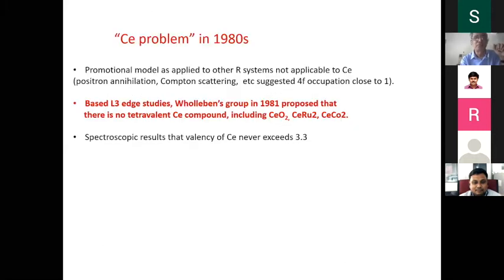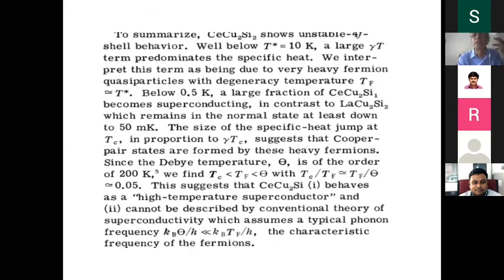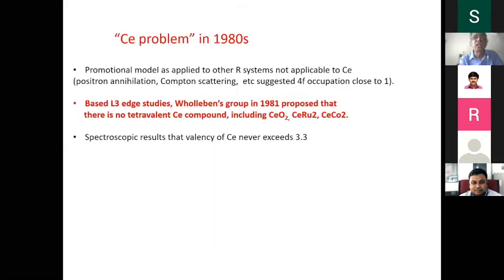And okay, so people started looking for other cerium materials where you can find superconductivity, and other cerium materials where you can talk about valence fluctuation and valence transition. They came across a problem that there are a lot of inconsistencies. For example, even cerium dioxide: chemists, including physicists, all think that cerium in it is tetravalent, which means there is no 4f electron in the cerium.